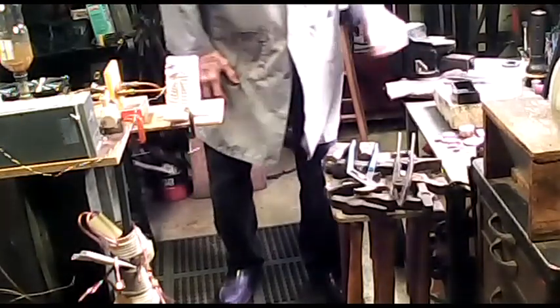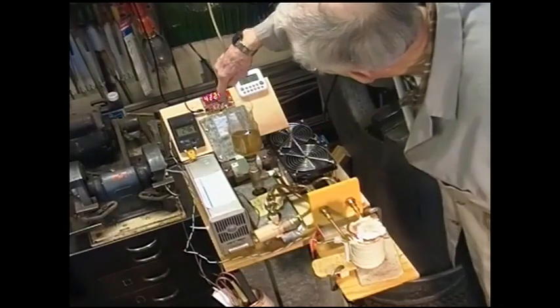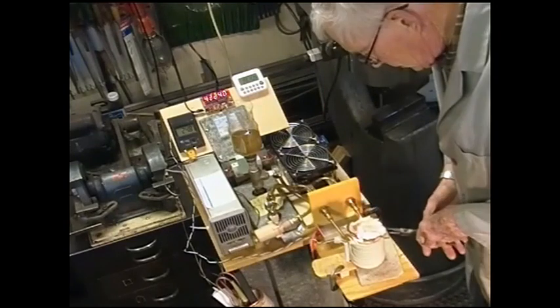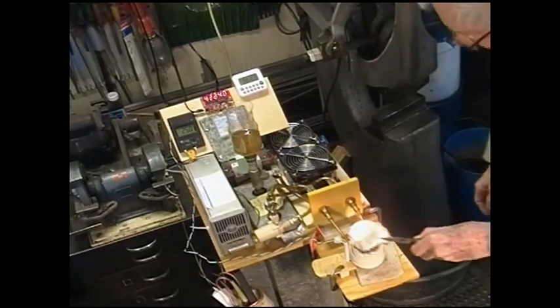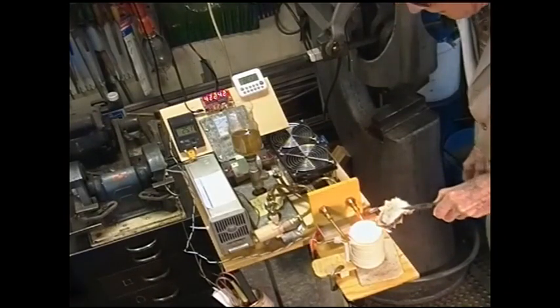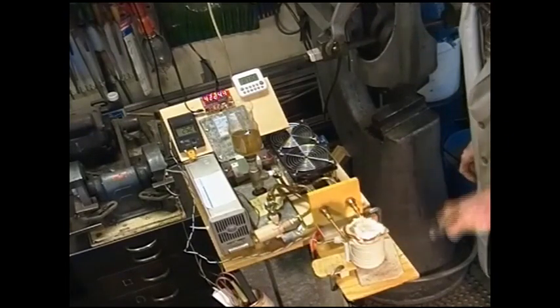6 minutes and 40 seconds, 24.6 Celsius on the water. Current has dropped back to 31 amps. I bet you something melted in there. Sure enough, it did, and it's actually bubbling there. I suppose you can't see it. The crucible ended up, it looked full, but it's only about 1/3 full. The copper is melted and bubbling at 7 minutes.